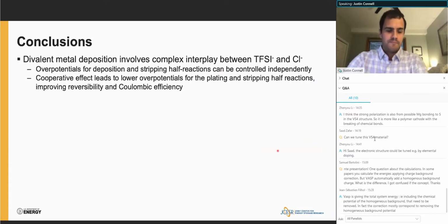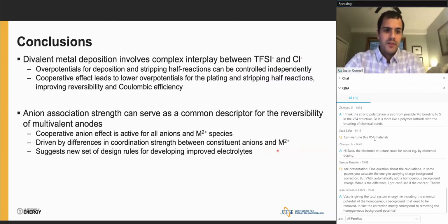So to conclude, it's shown that divalent metal deposition really involves a complex interplay between the different anions present, highlighting specifically the TFSI chloride system, where the overpotentials for the deposition and stripping half reactions can really be controlled independently based on the specific anions. And via their cooperation results in lower overpotentials for plating and stripping and improvements in coulombic efficiency. We've shown that this anion association strength can serve as a common descriptor for reversibility of multivalent anodes, where this effect appears to be active for all of the anions and divalent cations that we studied in this work.